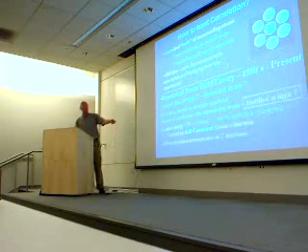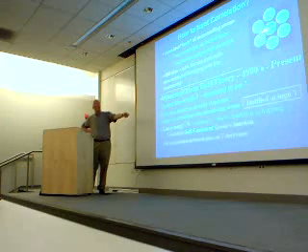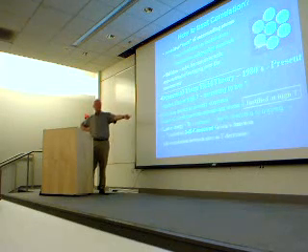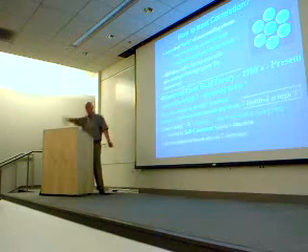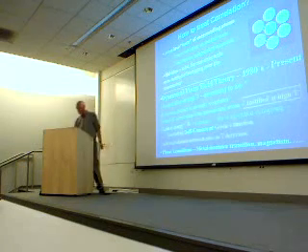And it's a self-consistent problem, because if we take this as iron, for example, if this is an iron atom, then that's an iron atom. And they need to be equivalent, even though you're treating this one a particular way and these as a bath. They need to be consistent with one another. So if it's a self-consistent Green's function, then you can have this bootstrap effect and get metal insulator transitions, phase transitions, and describe magnetism.